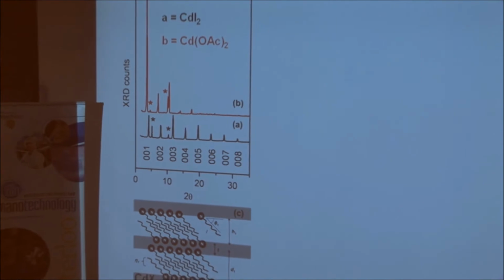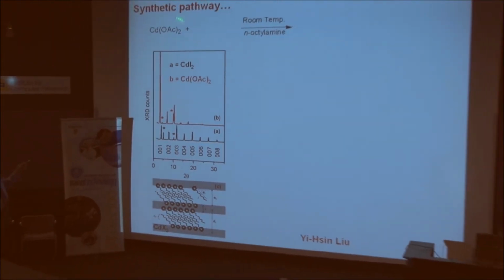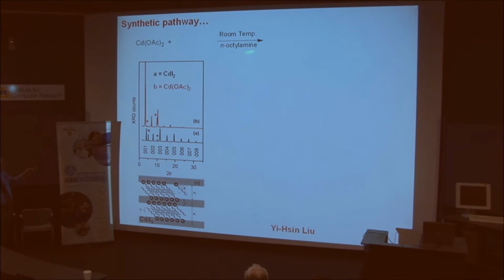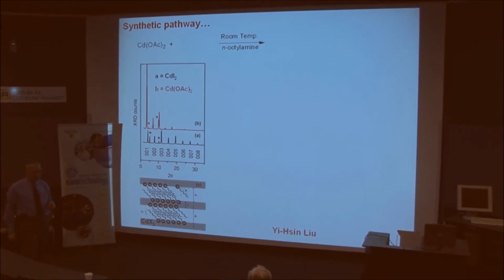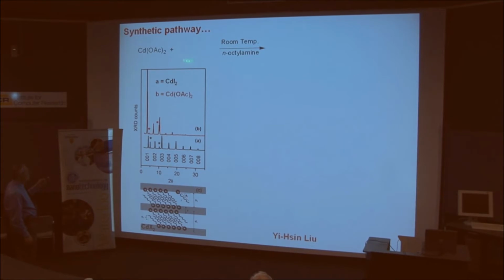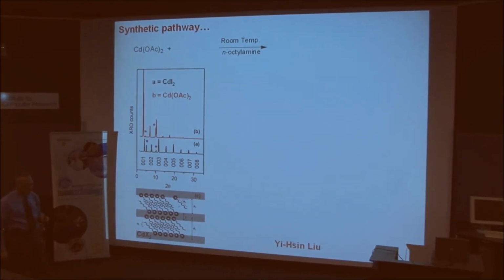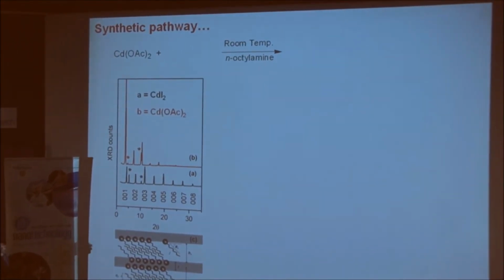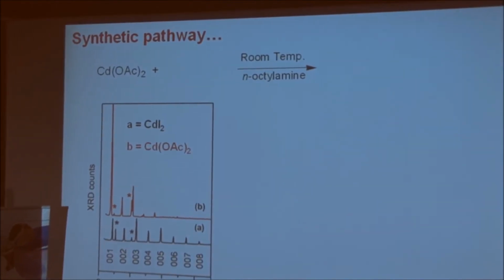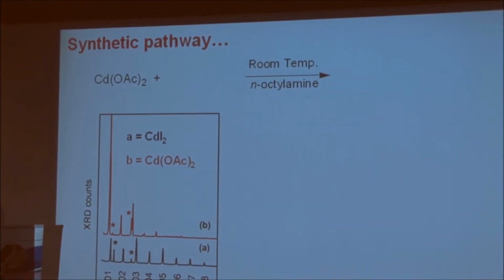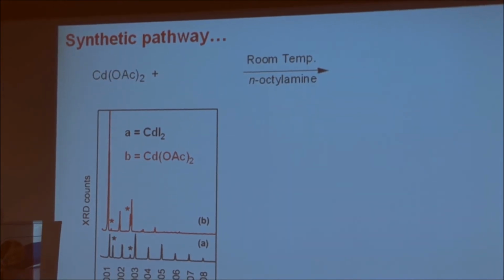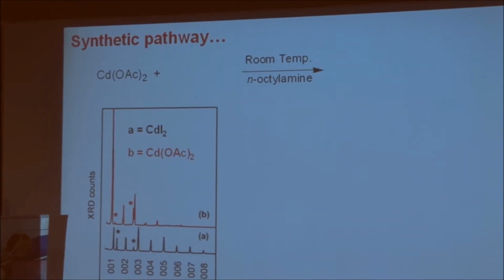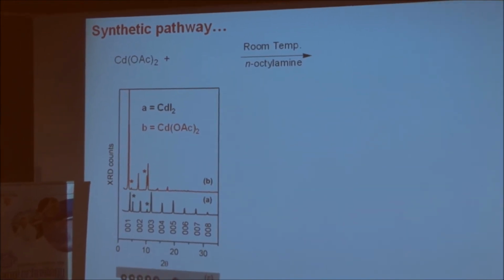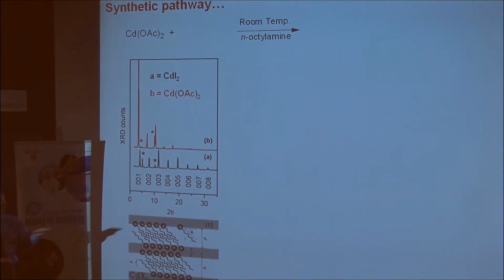So let me show you that the synthesis involves dissolving a cadmium precursor in N-octylamine. N-octylamine is the solvent for this process. And we noticed that when we combined N-octylamine and cadmium acetate, we got a pseudo-gel-like, pseudo-solid-like material. My student, Yi-Shin, was able to get some of that into the powder diffractometer and take a diffraction pattern.